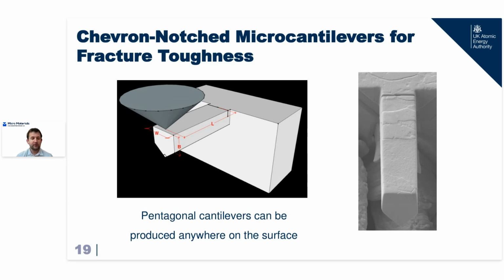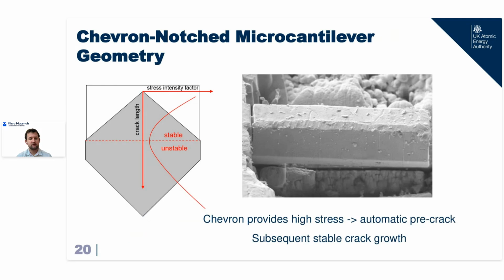But the real trick he came up with is this chevron geometry of the pre-crack you induce near the fixed end of the beam. By milling out this triangular chevron geometry at the top, you have a very, very high stress intensity factor right at the surface of your beam, where your bending stresses are also highest. So you automatically pre-crack your sample. You end up with a very, very sharp crack, self-inducing almost from the surface.